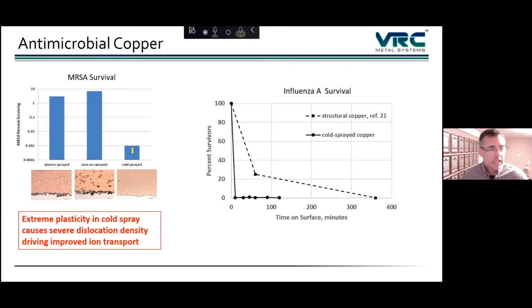Another interesting case is the use of copper for antimicrobial coatings. So there's been a lot of work done in taking copper in general and using it as antimicrobial. It's even better when you cold spray it, though. You could see here an example of 3 different coatings on the left. These are 2 thermal spray coatings and a cold sprayed coating. And this is the survival rate of MRSA bacteria. So here you see a significant reduction in the survival of the MRSA on the cold sprayed material in